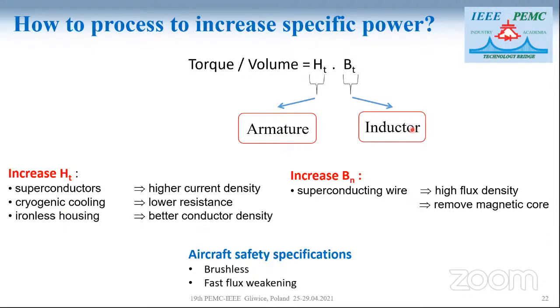And in this way, in all cases, you can use an ironless housing or a small back iron, and so you can obtain a better conductor density without iron teeth. The second way is to increase the magnetic field produced by the inductors. In this case, we use superconducting wire, so you can obtain a high flux density and remove the magnetic core. And we need to do that taking into account aircraft safety specifications, for example, a brushless system and fast flux weakening.